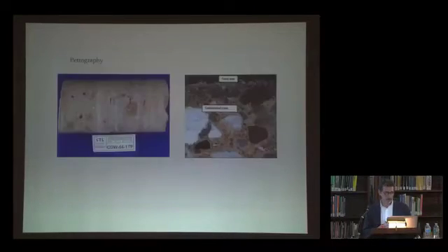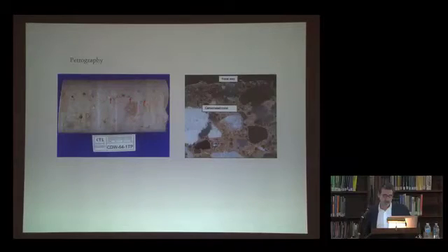And I'll tell you why in a little bit. In addition, representative core samples of the different types of concrete were also taken and subjected to a number of tests. On the left, you can see a core with the exposed surface at the left, and in the image on the right, an indicating stain showing the depth of carbonation, which is the alteration of material due to exposure, which, as you can see here, or I will point out, is not very deep.